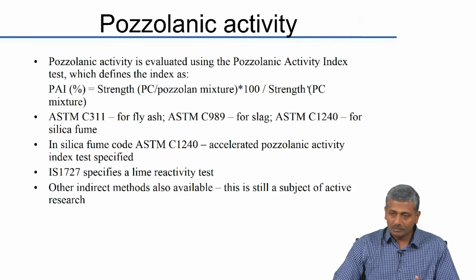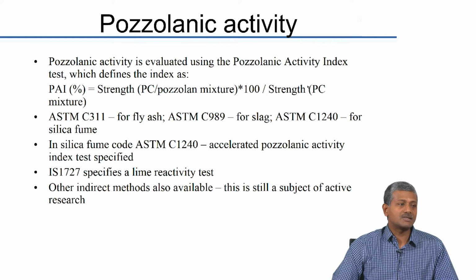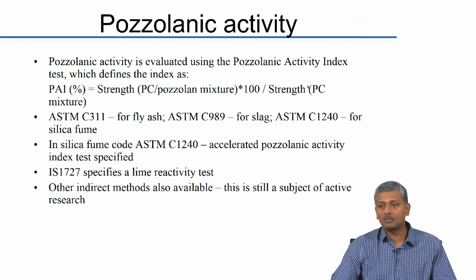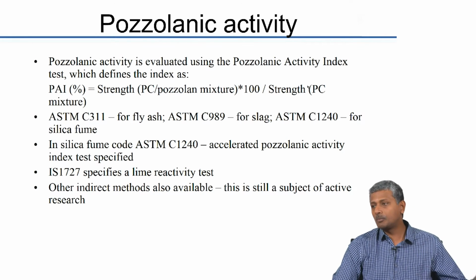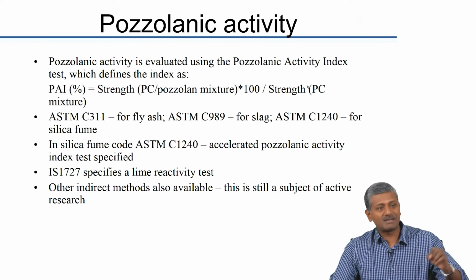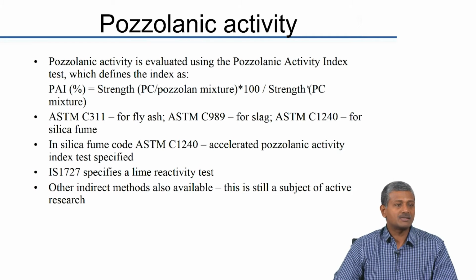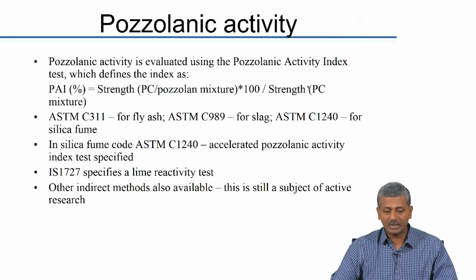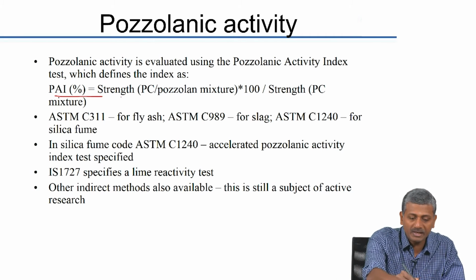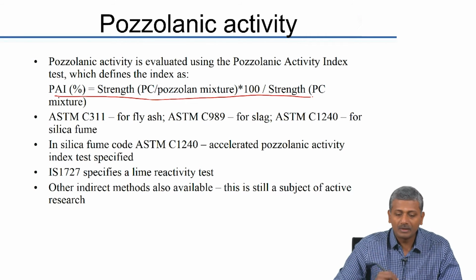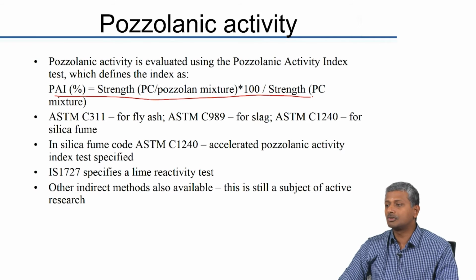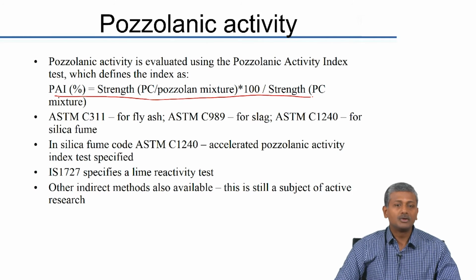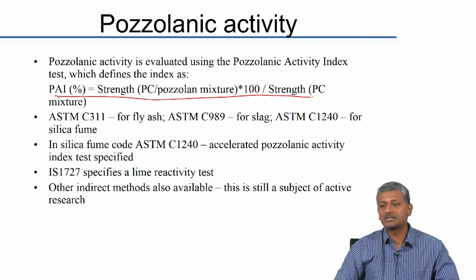The most commonly used test is a regular strength test. You prepare a mortar with plain Portland cement, and the same type of mortar at the same flowability with a system which has the Portland cement replaced by a certain percentage of your mineral additive. Then you represent the pozzolanic activity index as the ratio of the strength of the Portland pozzolan mixture to the strength of the plain Portland cement mixture.